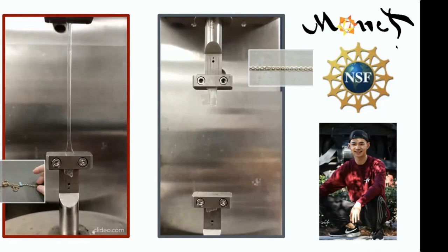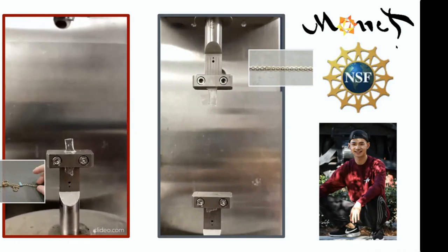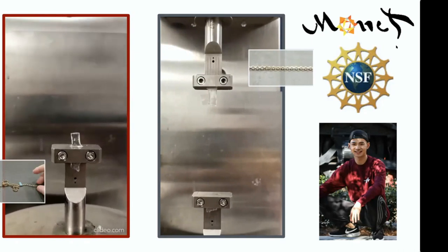And although this is a long way from being a new material for tires or for biomedical implants, the level of reduced fatigue and wear that is seen here should be enough to increase the lifetime of this hydrogel under repeated cyclic use by a factor of 2 or 4, which if you think about that translating in the future to the rate at which materials hit landfills or the rate at which people need replacement surgeries, we think can have a big impact. And so with that, what I'd like to do now is turn the floor over to